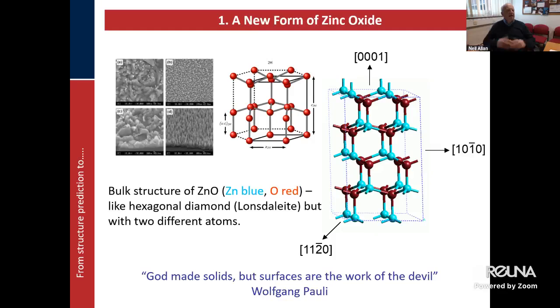But what we were finding for these 0001 films was that the cation and the anion layers were collapsing, coming together, forming hexagonal rings, as we show here. And so they repeated it over and over again. I could find no references to it in the literature. And eventually I said, you must be right, I'm wrong, which is something that students like to hear.